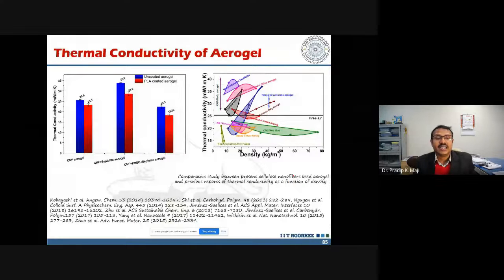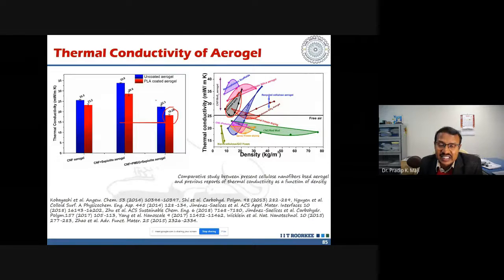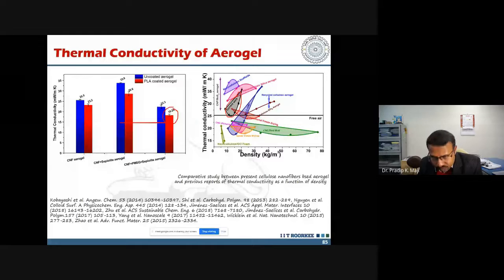So the thermal conductivity, as I told you, comparing to other material and reported values, this is our work. Now we have reached a product where we are able to reach 18.28 milliwatt per meter Kelvin. You can see this CNF, PMSQ, CIPET aerogel, we have reached up to 18.28 milliwatt per meter Kelvin. It's a huge reduction, less than the silica aerogel people have reported.